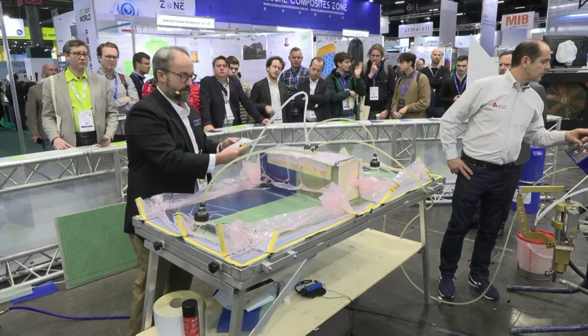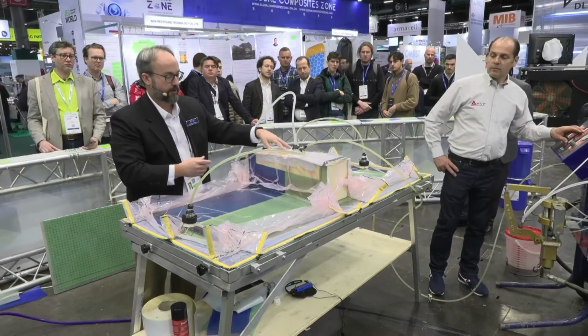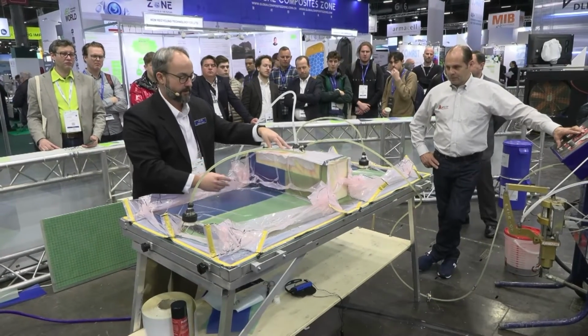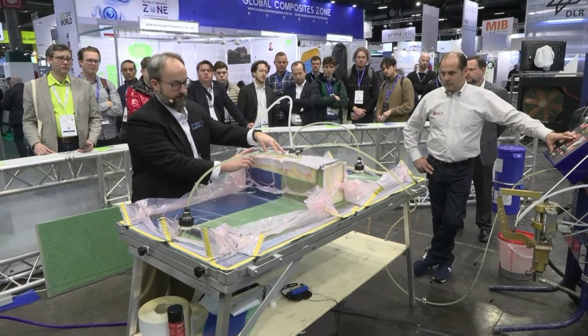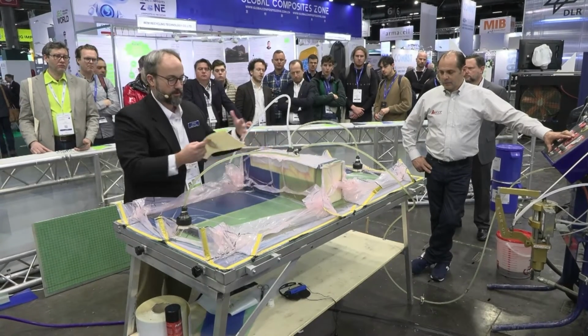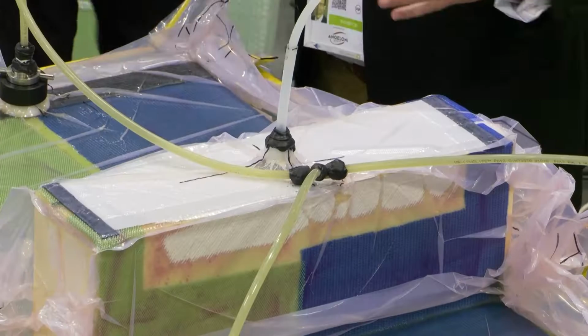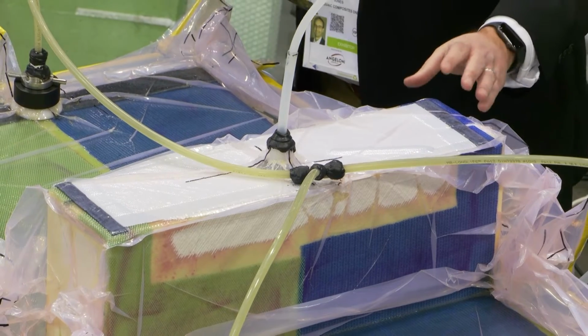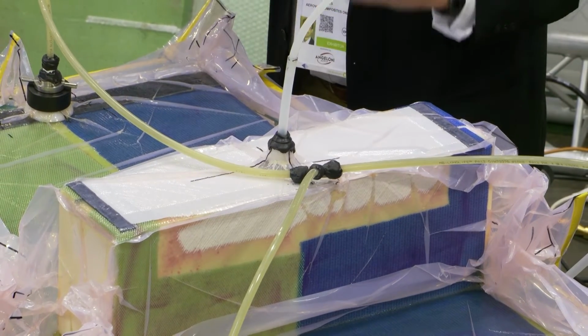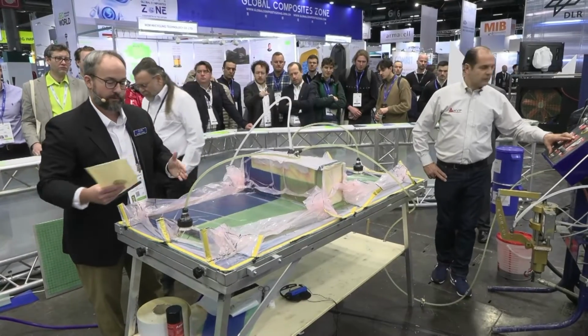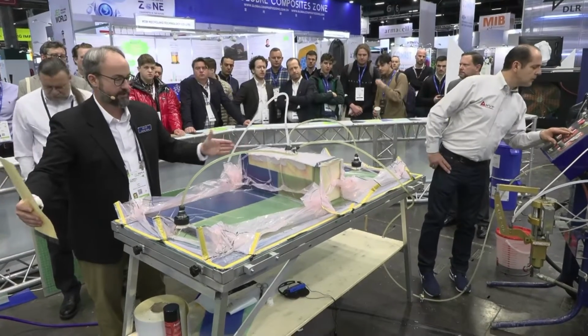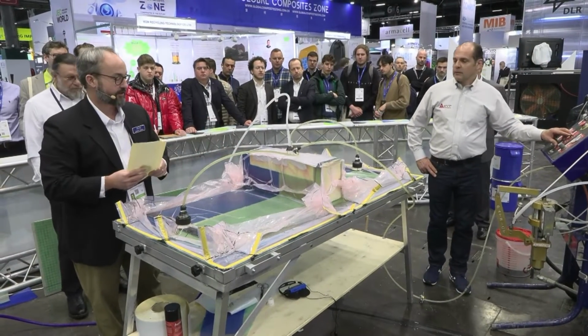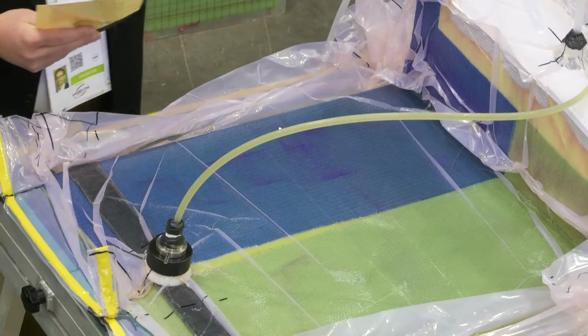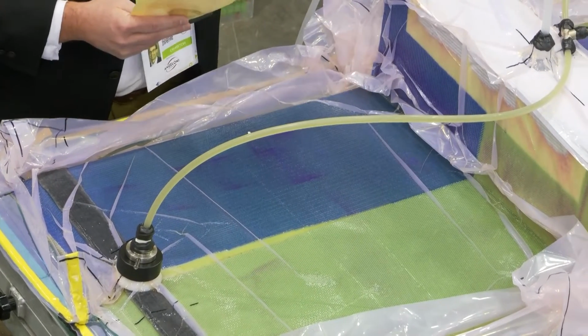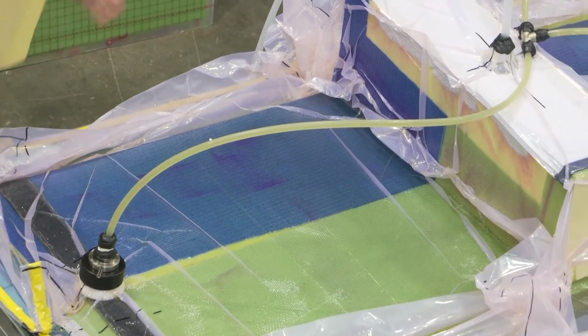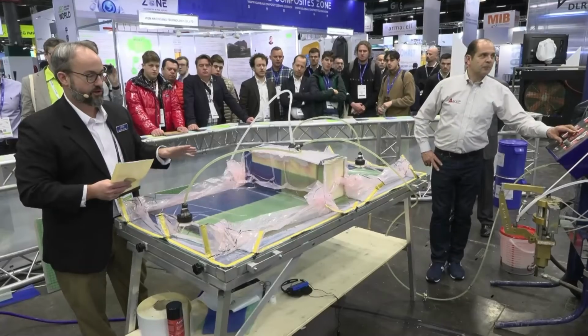And so that is a really nice product. We can put it directly on our laminate without any risk of drawing out resin or creating dry spots. So this configuration is kind of a simulation of, say, a large deck panel or a floor or a bulkhead. We would have about 1.5 meters between these stiffeners, and we could scale this up to, we've done parts up to 100 meters long by 30 meters wide. Same concept, just a larger process, all injected at one time.